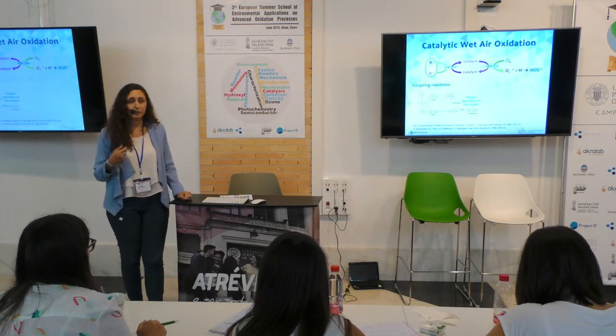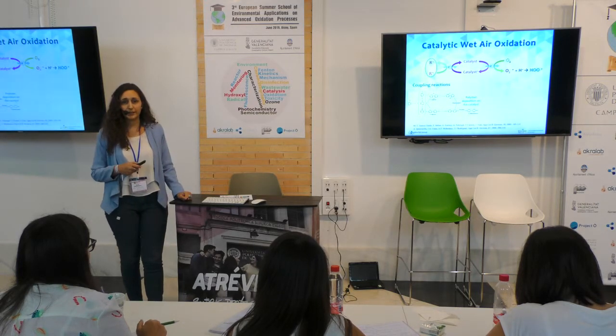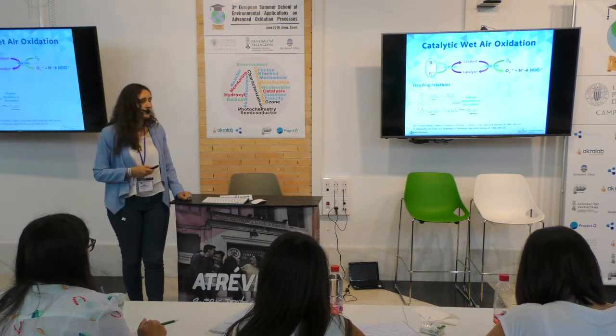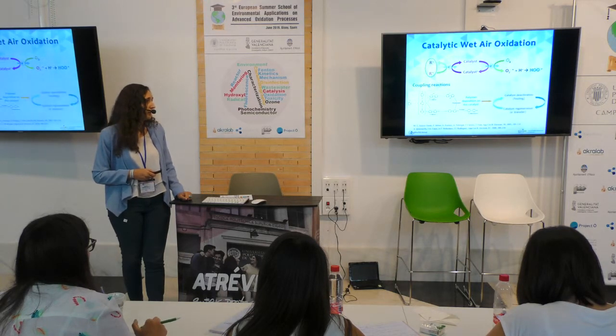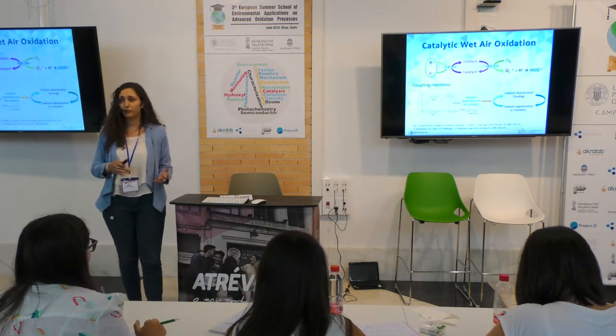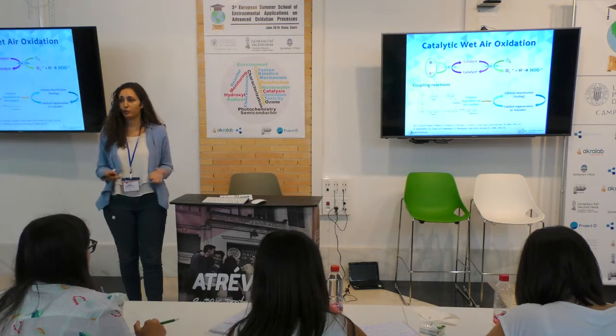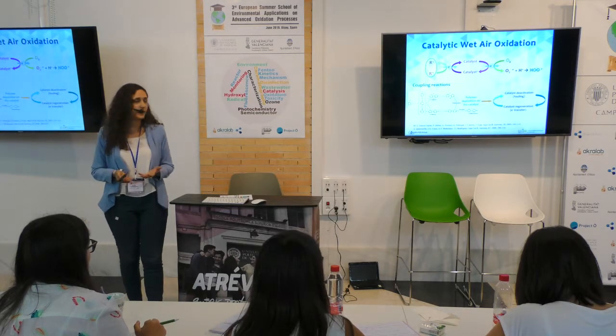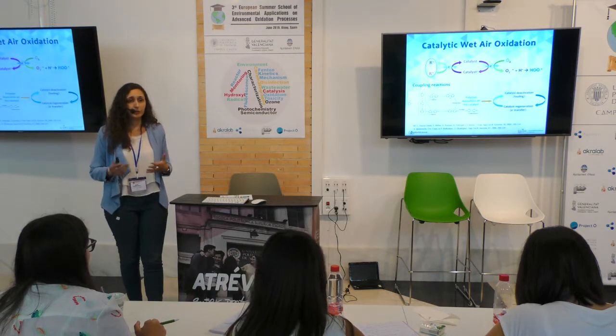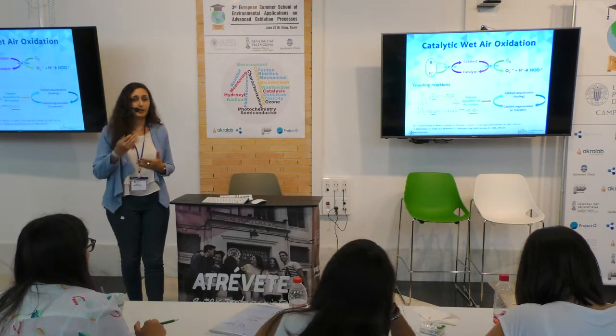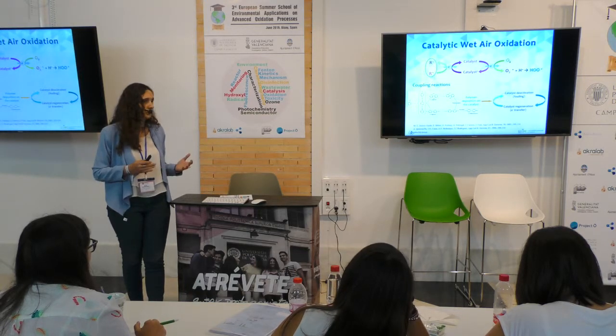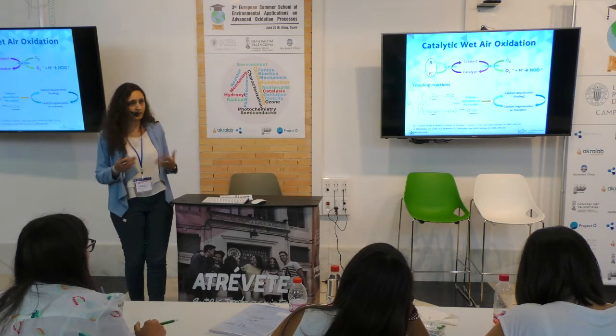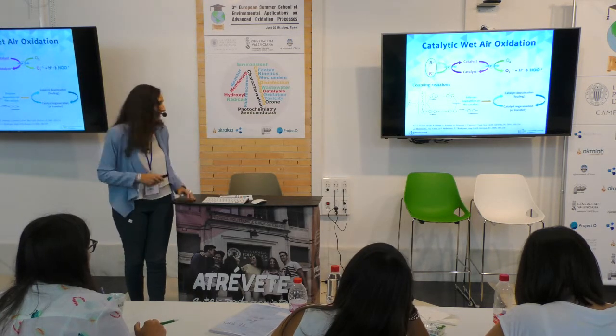These polymers will be deposited onto the catalyst, giving us a dual effect. On one side we have catalyst deactivation by fouling — we cover our active sites. But these polymers will also donate the electrons we need to regenerate our catalyst. So our polymers are bad and good at the same time.